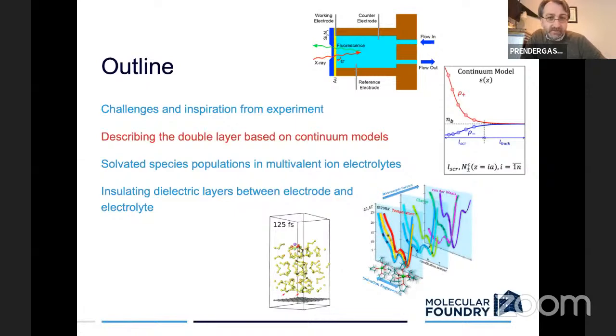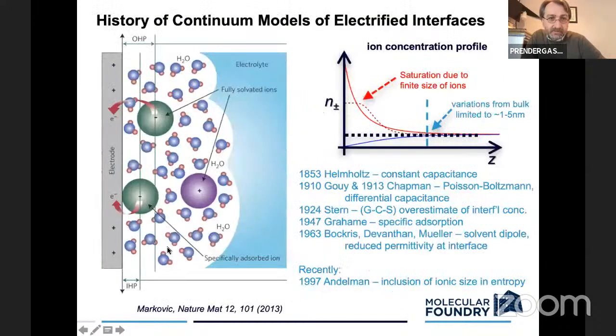Okay, so let's talk first a little bit about models, and continuum models in particular. We did hear a little bit about this earlier in the week, and this picture appears quite a lot from this review in Nature Materials by Nenad Markovic. The theory of electrified interfaces is pretty old. It goes back to the middle of the 19th century to Helmholtz, and it has evolved every 60 years or so. And we're at a point now where, if you do things the right way, you realize that your concentration should not blow up at the interface because the atoms have a finite size. They can only pack together in certain densities. There's a limit there. We also know that the dielectric screening near the interface is reduced because you have fewer species there to do that work. And then there may be details of specific adsorption that you have to care about too.